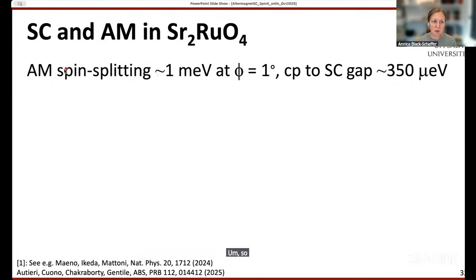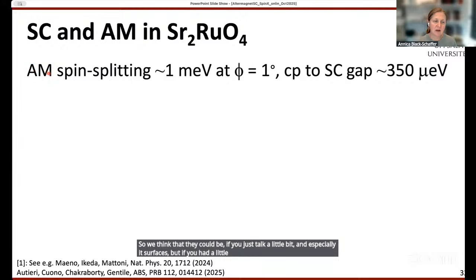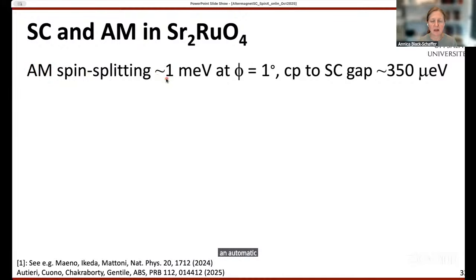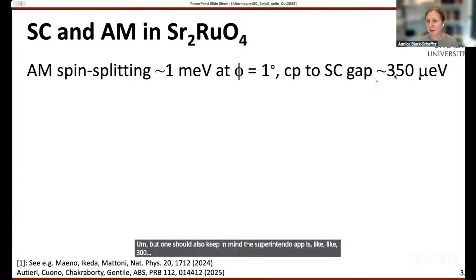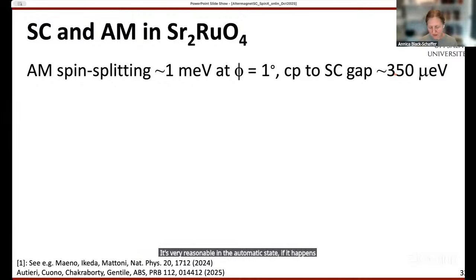So we think that if you distort a little bit, especially at surfaces, you would have an altermagnet spin split that's around 1 meV. So it's small, but one should also keep in mind the superconducting gap is like 350 micro eV. So even if this is very small, you're comparing with an even smaller number. So it's very reasonable that the altermagnet state, if it happens, should influence the superconducting state in this material.